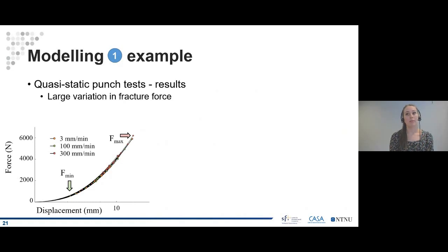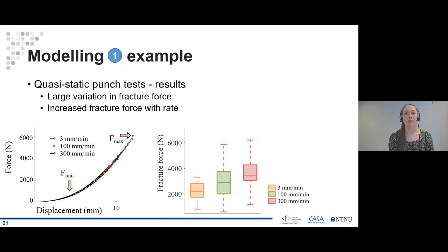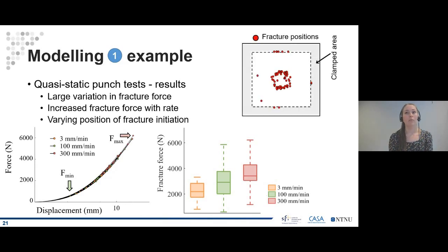First off, this figure shows the force displacement curve of all the different tests. We see that we got a large variation in the fracture force, and it ranged from 590 to 6,200 newton. We also saw that the fracture force increased with the loading rate, and this is shown by these three different box plots. Also, we saw that the position of fracture initiation varied. Most of the plates fractured around the center, but we also got some fracture initiation outside the center. These are shown by the red dots.